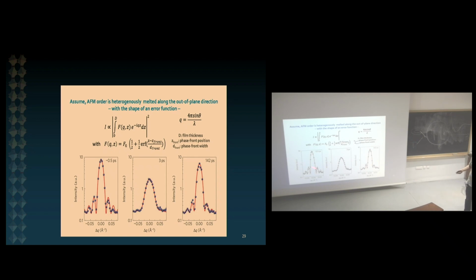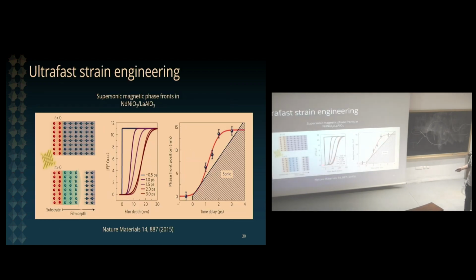So you can Fourier transform this data to obtain a spatial shape of your order parameter. Before the laser pulse comes, you have a sharp interface between the substrate and film, and then as time goes by, this interface is moving inside, and it's becoming broader. So this is reflecting a propagating phase front that is moving across the film. By doing this experiment, you're actually tracking the speed of propagation of this phase front into the thin film. And we see that this exceeds the speed of sound quite considerably. So it's a supersonic propagating phase front.